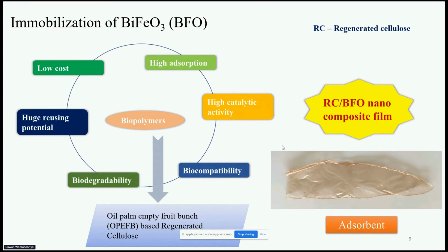In this research, oil palm empty fruit bunch based regenerated cellulose was selected as the biopolymer to incorporate the selected bismuth ferrite powder, and this research aimed to synthesize regenerated cellulose bismuth ferrite nanocomposite film as the photocatalyst to evaluate the degradation of dyes.